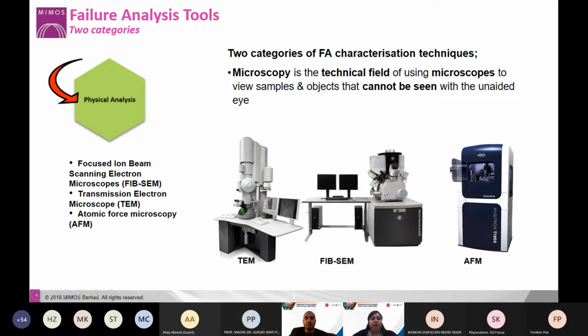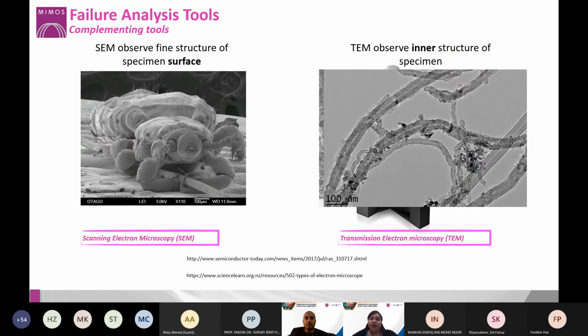All right. So this is the difference between a SEM, scanning electron microscope, and a TEM, transmission electron microscope. For SEM, the electron beam will only give the specimen surface information because the electron beam doesn't transmit through the sample. It just does the scanning at the top part of the sample, so you can only get topography information on the surface. Whereas with the TEM, you can observe the inner structure because the beam will penetrate the sample and you get more information.